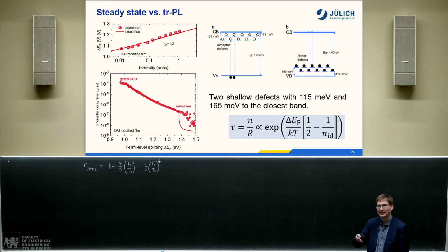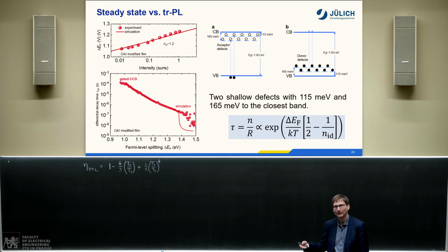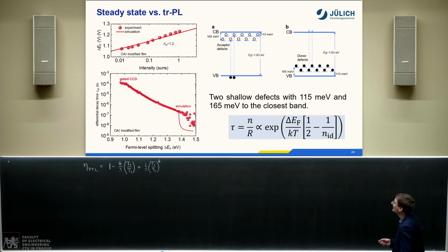So whenever you have an ideality factor that is not 2, then even without having radiative recombination, the lifetime will change the whole time, until eternity. That means the question of getting a very long lifetime becomes at some point only a question of measuring for sufficiently long. That's what I want to say. It's not a competition of having the best cell on the planet. It's just a question of what this decay time is, and then measuring for a while.